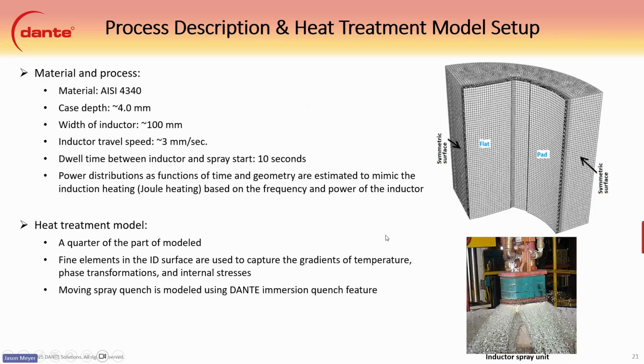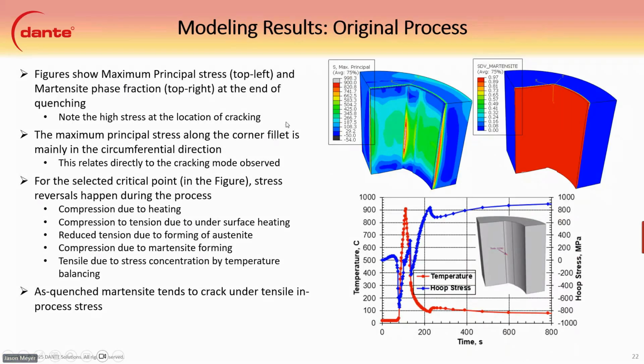We used fine elements on the inner diameter of the surface. We used much finer elements to capture the gradients of temperature, phase transformation, and then any internal stresses that are formed from the induction hardening process. The moving spray quench was modeled using DANTE's immersion quench feature. It's a nice subroutine used for quenching these.